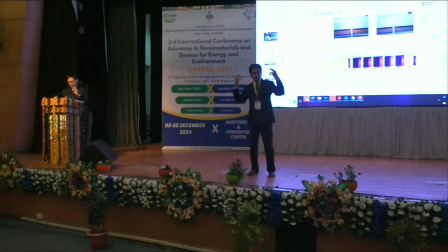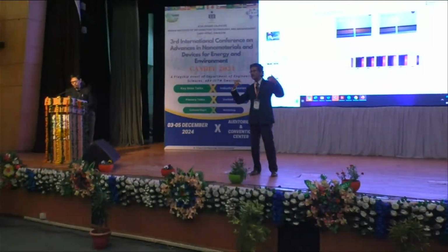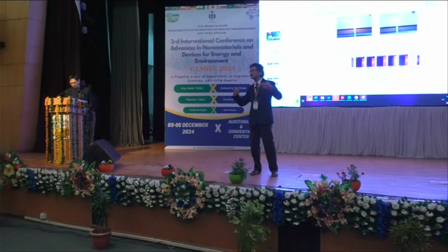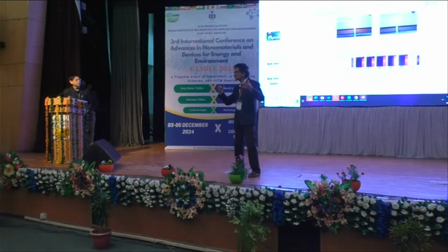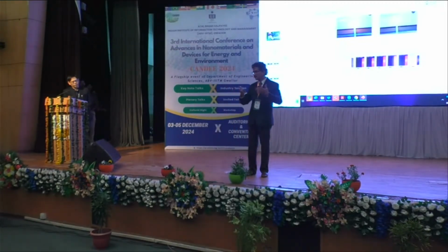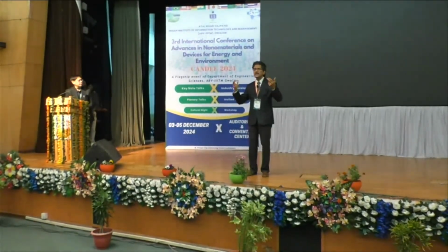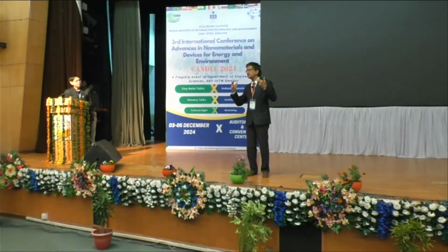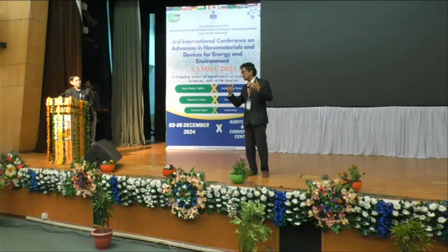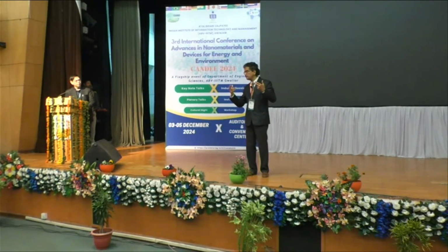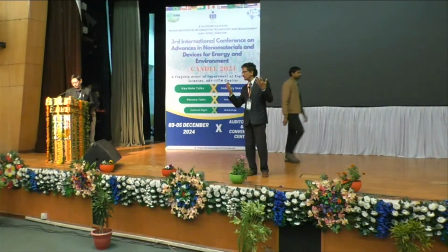It has been sold to the battery world as solid electrolytes don't catch fire because they're made of ceramics and can withstand high temperature. But the problem is they still suffer from short circuits, because ceramics have grain boundary defects and the dendrites go through the defects and eventually short it.